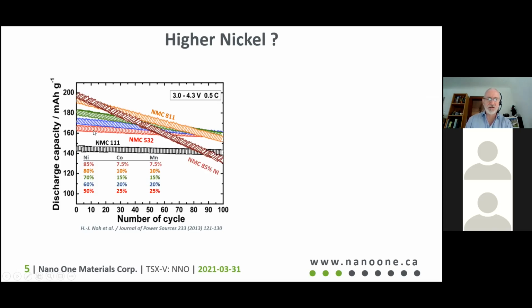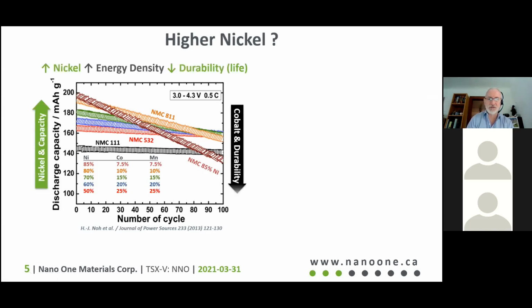As you increase the nickel concentration up to here, which is 85, and believe me, now they're going up to 95 to get as high as they can, the capacity goes higher and higher. They're now aiming for about 220 milliamp hours per gram of material. But as you can see, the higher you go in capacity, the problem is that the durability goes down because the slope gets steeper and steeper. So over a very short number of cycles, it loses a significant amount of its capacity.